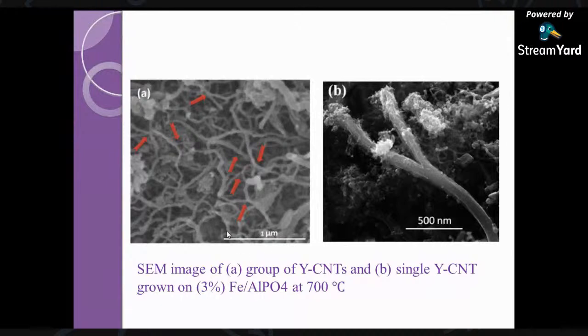Then you can see from these SEM images the formation of Y-shaped carbon nanotubes. So we achieved this morphology of carbon nanotubes, which have a junction type or a Y-type junction. We call it Y-shaped carbon nanotubes. And this happens in this optimized condition of 3% iron loading on this catalyst at a temperature of 700 degrees centigrade. So we can see more networks or more Y-shaped morphologies happening here. So this is a good, interesting result that is obtained.